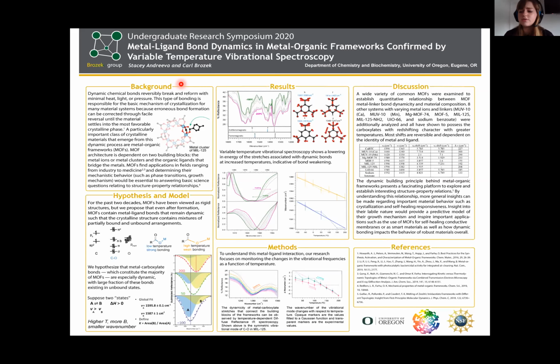So my project revolved around studying dynamics in porous MOF materials and trying to establish a fundamental impact of dynamic bonding on the behavior of this material, such as determining what's the relationship between the labile bonding and conductivity that could enable self-healing mechanism in these materials. So you might ask, what's so special about MOFs? They're crystalline microporous materials noted for their enormous structural diversity and versatility. And interestingly, they emerge from dynamical bonding formation process dictated by dynamic bonds, which are sensitive to induced stress.